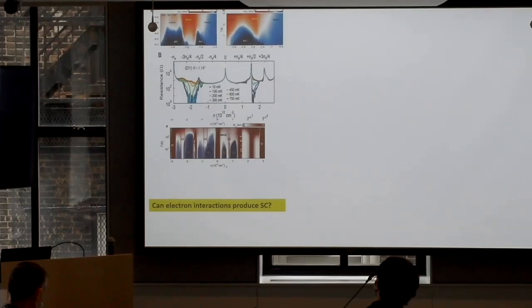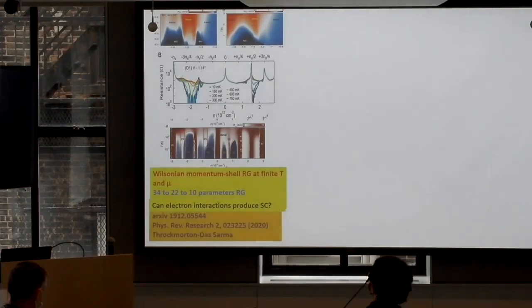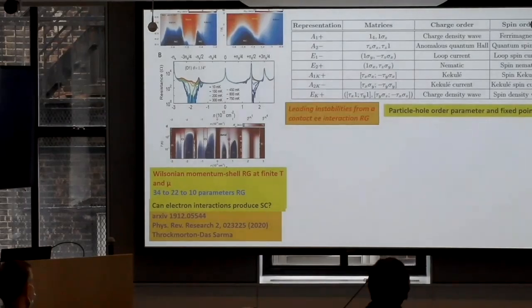But since we are theorists, I had to do some RG calculation showing that we can actually calculate electron-electron interaction in this superconductivity. When you do RG in a complicated system, you find superconductivity everywhere. This is a very formidable RG. We have a postdoc, Robert Throckmorton, who, I said the full RG is impossible. It's a 34 parameter RG. Basically, people do 1 or 2 parameter. With symmetry, it could reduce to 10, but this is really a 10 parameter momentum shell RG. And what he found is that almost every phase you could think of, there could be a phase transition. This is the problem with RG. It tells you what is possible, doesn't tell you what actually happens.